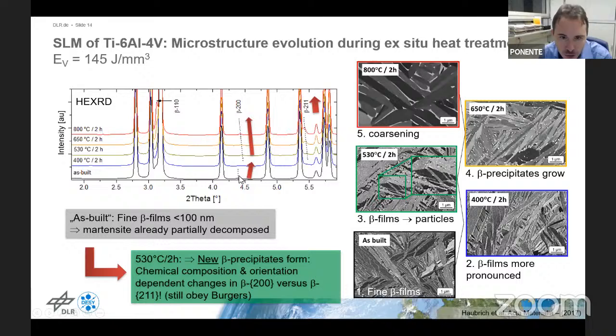You see that this beta signal changes, disappears a bit at 400, and then at higher temperatures, we get a beta 200 signal, and we also get other beta signals growing in the spectrum that are very clearly discernible. So one thing that we directly see, the beta phase changes due to the heat treatments. It does change in terms of chemical composition, and it does change a little bit in terms of orientation.